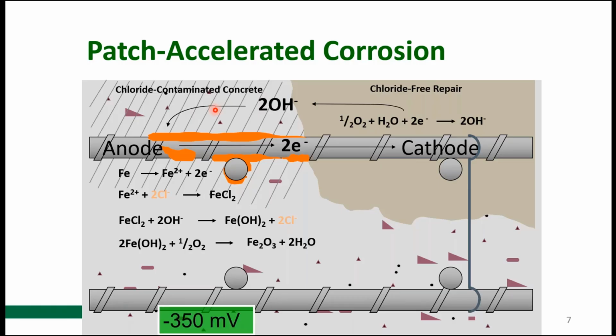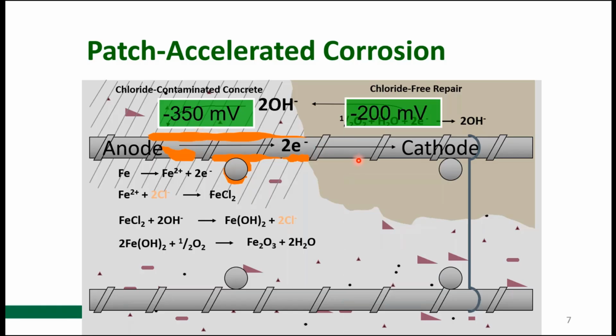And that happens because you have different potentials, or essentially voltages, in the steel, which result from the environment around the steel. So where you have salt contaminated concrete, you may have a potential something like minus 350 millivolts, whereas in the concrete without chlorides, you might have a potential of only minus 200 millivolts. And you have a voltage difference here. And the area that's more negative is always the area that's going to corrode. And that's going to push current to the area that is being protected by the corrosion. And so that's the mechanism that happens in the background.